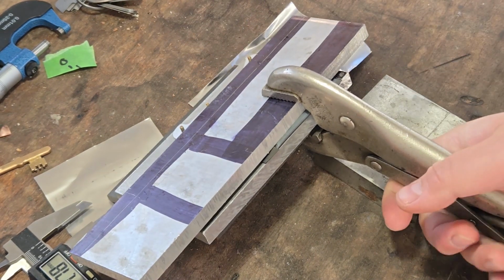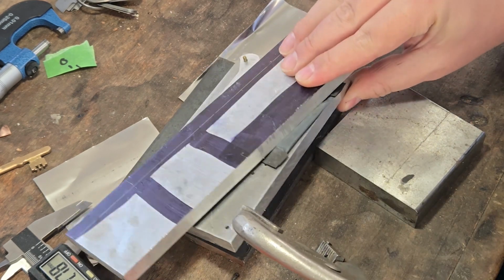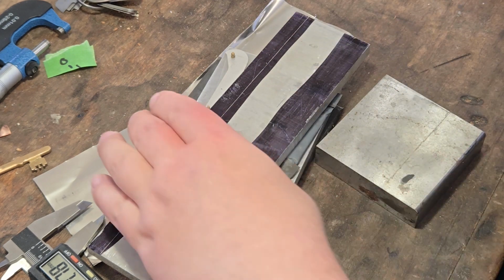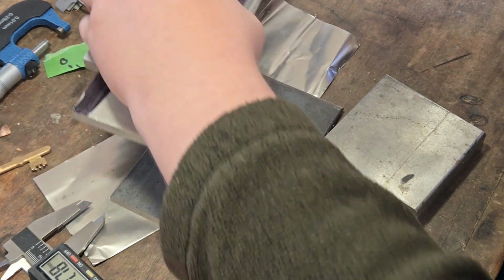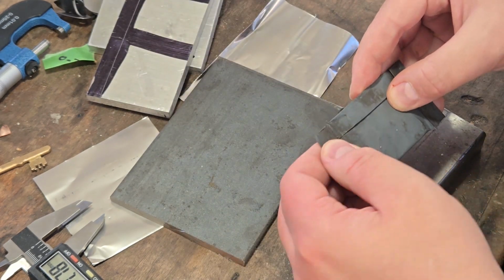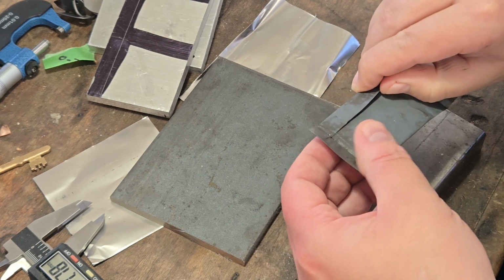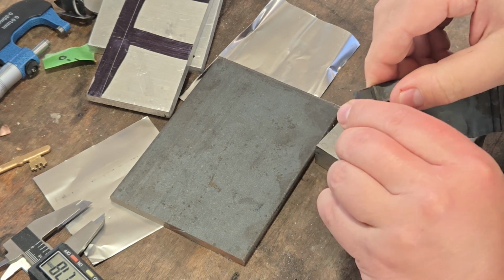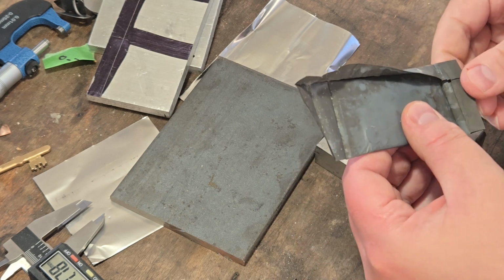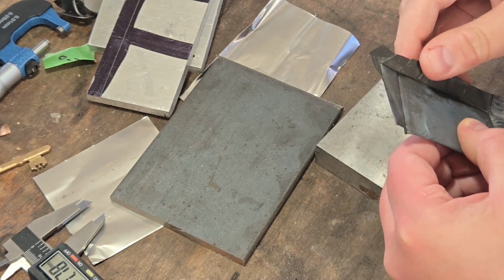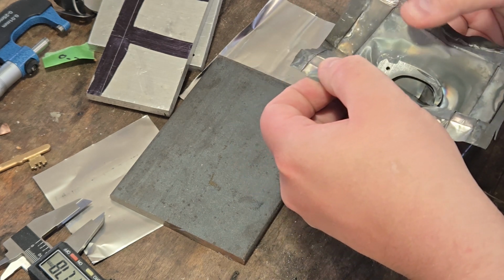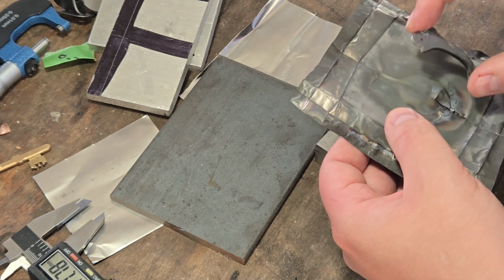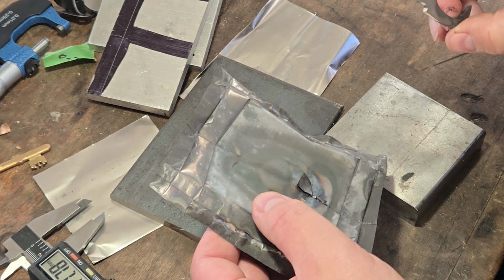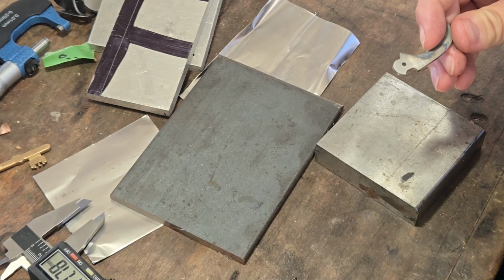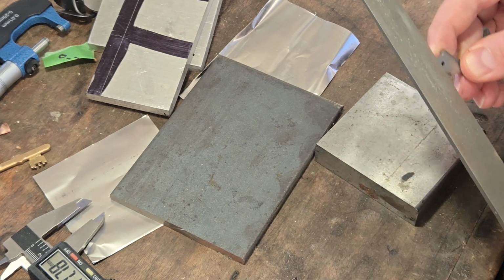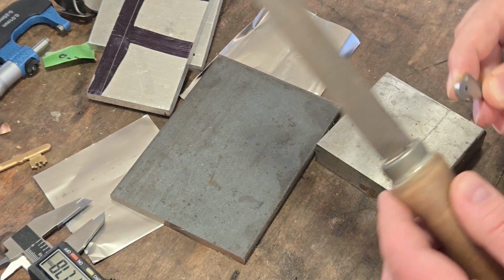Alright, so we can take it out of the plates. Cool. So the cooling rate is not too critical for this, as long as you cool it faster than 2 minutes, which this easily will have done. Okay, yeah, that's in pretty good condition. Bit of oxide, but not too bad. So that should be hard now. Yeah, that's hard as a coffin nail, as they say.